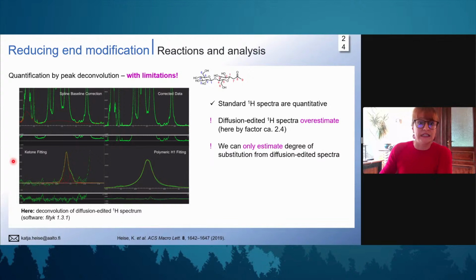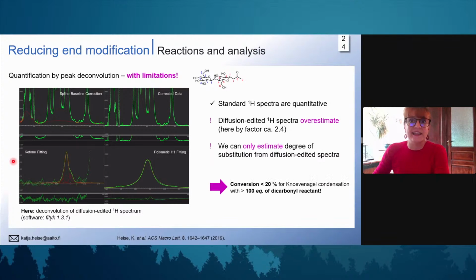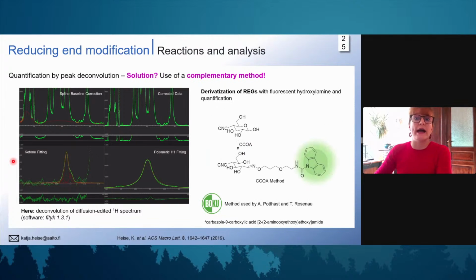And this was for the ketone functionalization, it was a bit disappointing, seeing that we used a huge excess of reactants, which is very often the case for cellulose modification, and we only had a conversion of less than 20%. If you want to have reliable quantification of reducing end group modification, you go back to the wet chemistry methods. This is one example.